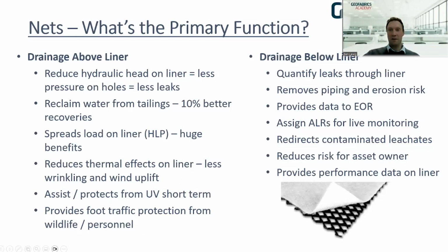In terms of drainage below the liner, we can quantify leaks through the liner, so it gives you an ability to qualify the performance of your primary liner. Removes piping and erosion risk below the liner. Gives data to your engineer of record on site. Gives them a bit of confidence in how it's performing. And you can actually assign action leakage rates for live monitoring. So as I said, you can live monitor your liner, so then you can understand when it's underperforming or performing as it should. Reducing your risk, for the asset owner, in terms of failures and contamination of subgrades. So ticking that box with the EPA, and it provides long-term data on your liner, as I've said.